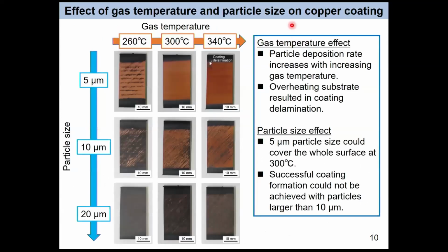So let me move on to the result of coating on CFRTP. Now we can see the temperature effect in the horizontal direction and size effect in the vertical direction. First, we focus on the gas temperature effect. For example, in the 5 micron particle case, the deposition rate increases with increasing gas temperature. But in the case of 340 degrees, coating delamination was observed. Overheating the substrate resulted in coating delamination.